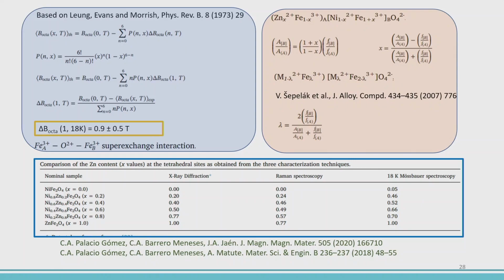I want to say also another thing about Mossbauer. We can also determine the superexchange interaction on the octahedral site by using this proposed equation, assuming some interactions. In our samples we determined 0.9 Tesla, and this is very close to the value reported by Leung and Evans in 1973, that was about 1.2 Tesla for the exchange interaction. It is good, let's say, it is within the range of values.